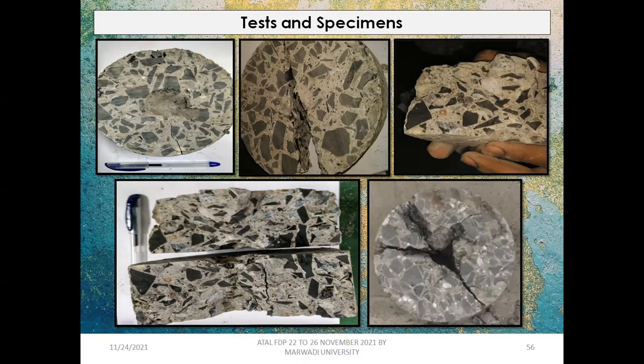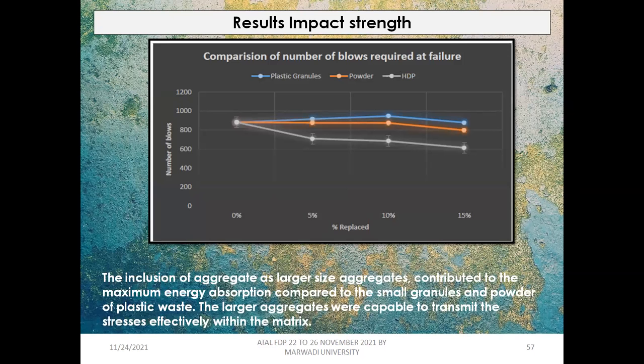I'm not sharing the detail, but I would like to mention that it holds potential. That's what I said earlier also: we should not start hating plastic as a material, but it definitely holds special potential if you use it in a proper way, right? These are the impact results, which show how the HDPE powder and plastic granules performed in the test, up to the replacement of natural sand and natural aggregates. Definitely, plastic granules performed well in this case.